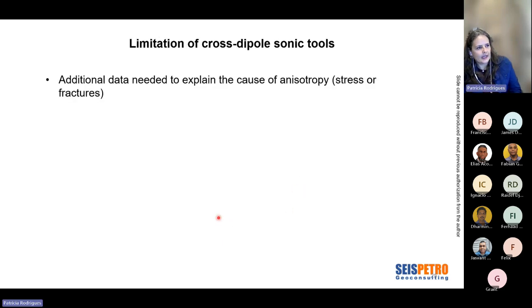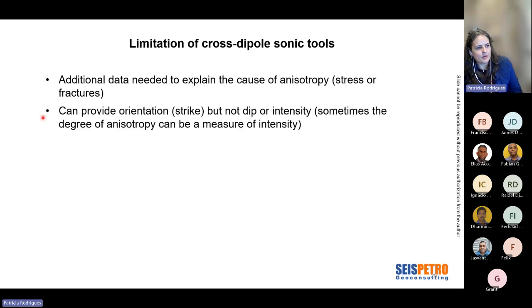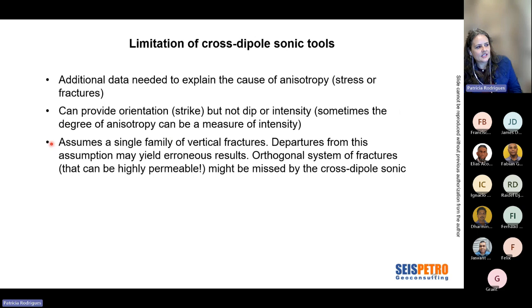Okay, so the limitations, as I already emphasized, is that you need additional data to explain the cause of anisotropy, whether it's stress or fractures. It can provide orientation, because you can calculate the direction of the highest anisotropy, and it will give you the strike. It won't tell you the true dip. It will tell you the intensity indirectly, because the degree of anisotropy could be a measure of intensity. But it assumes a single family of vertical fractures. So if you depart from this assumption, it may yield erroneous results.